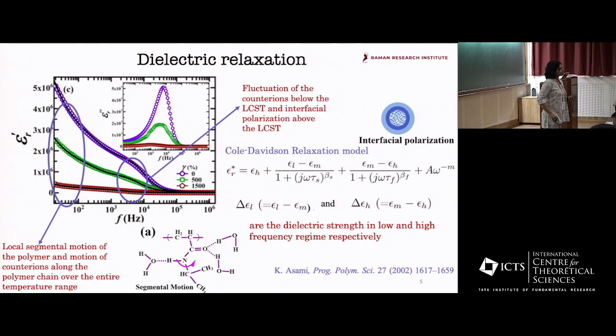So do you expect these two-step relaxation timescales to change if the surface is rough, like with hairy particles? We have done it for rough particles, and yes, you do see the two-step relaxation, because you'll always have some segmental relaxation, which is where the slower dynamics is coming from, and the fast dynamics is coming from counter ion fluctuations. Like I said, there are these sulfate ions on the surfaces, and sodium and potassium ions, and if they are there for rough particles, you'll also see that.